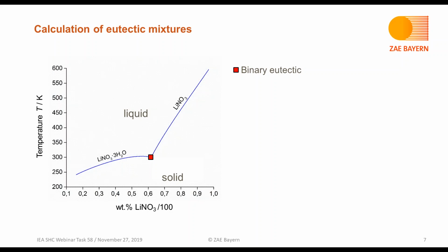Here, a simple phase diagram is shown in the figure. To keep it simple, the line illustrates the solubility threshold, the transition in temperature between the liquid and the solid. Above the line, everything is a liquid solution, and below, different solid phases precipitate. And as marked here in this system, lithium nitrate and water, there's a binary eutectic. And this is interesting to be used as PCM.